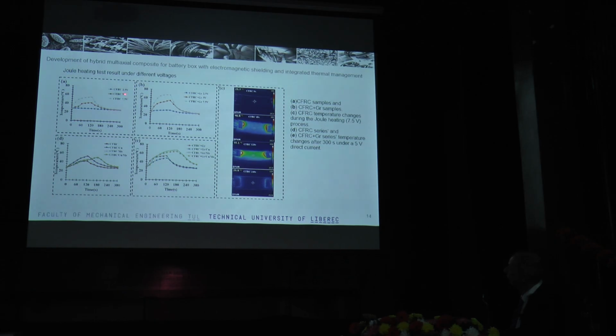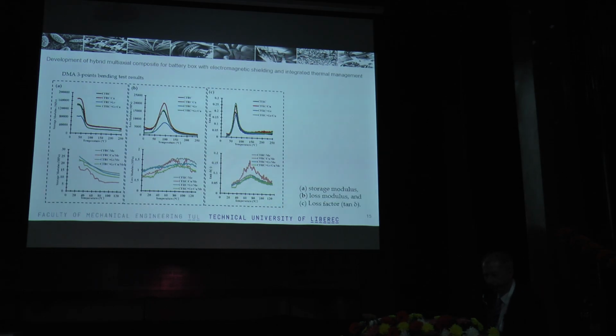This is the two layer of carbon, voltage 2.5, 5 and 7.5 volts, and it's possible to heat it for 2 minutes up to 60 degrees. After that we stop the current and observe cooling of this slab.